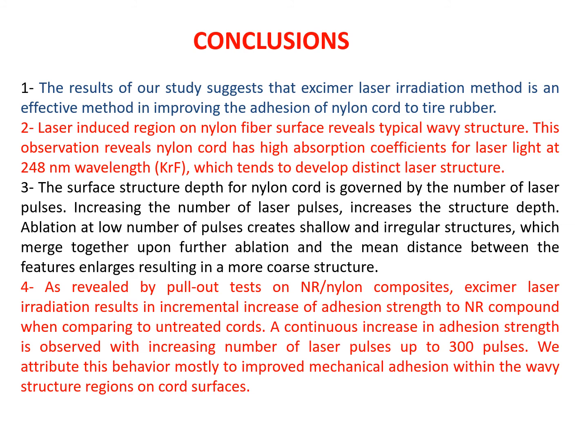As revealed by the pull-out test, on the natural rubber nylon composites, excimer laser irradiation results in an incremental increase of adhesion strength to the natural rubber compound when compared to untreated cords. A continuous increase in adhesion strength is observed with increasing number of laser pulses up to 300 pulses. We attribute this behavior mostly to improved mechanical adhesion within the wavy structure regions on cord surfaces.